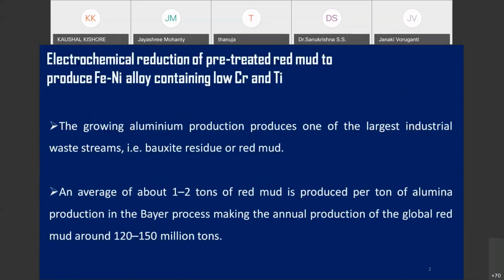Now, we have discussed the preparation of FeTi only from the binary slag. Now, I'm coming to the preparation of another kind of alloy, containing nickel, chromium, and iron, from red mud. A similar procedure is adopted, but some slight pre-treatment methods are different. In case of red mud, we have carried out one extra step that we did not do for the titanium slag. So we'll see.